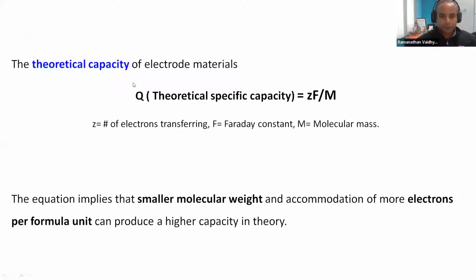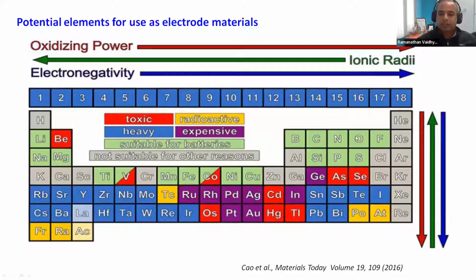And another important parameter for charge storage is what is called the specific capacity. If you look at the expression for specific capacity, which is Q, it is charge stored per unit weight of the material. And here you can see the denominator is molecular weight, which means if I have a small molecular weight, by default, I can get very high capacity. And if you look at what kind of elements would suit that, it has already been classified that you can have boron, carbon, nitrogen, oxygen, fluorine, lightweight atoms. If they can form your anode, that will be very attractive. And for the cathode, you want titanium, manganese, iron, nickel, copper, because you need redox activity very specifically for the movement of ions. And for the ions themselves, people have identified lithium, sodium, magnesium, aluminum, these types of lightweight ions as favorable.